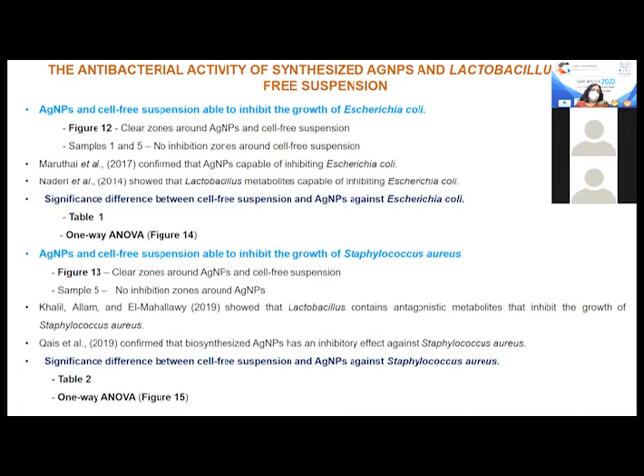Figure 13 showed clear zones around cell-free suspension and silver nanoparticles in S. aureus, showing that silver nanoparticles and Lactobacillus metabolites contain antagonistic substances to inhibit the growth of S. aureus. Also, according to Table 2, cell-free suspension indicated higher inhibition zones against S. aureus than silver nanoparticles for all 4 samples. One-way ANOVA further confirmed the significant difference.